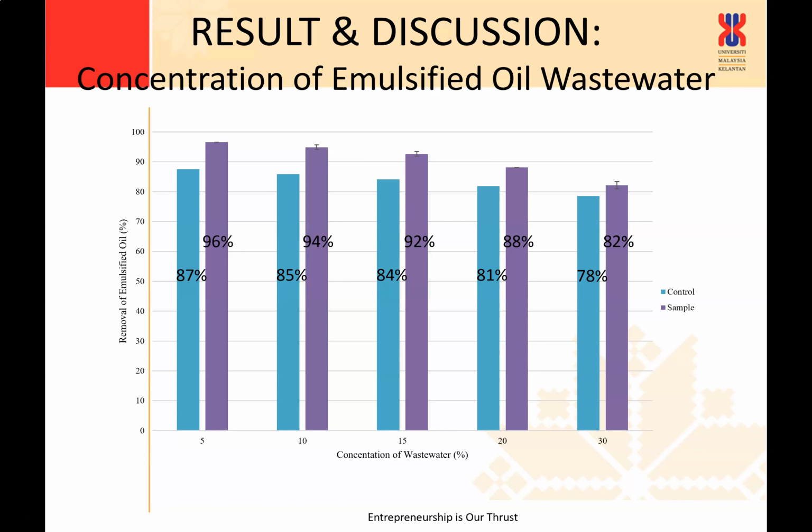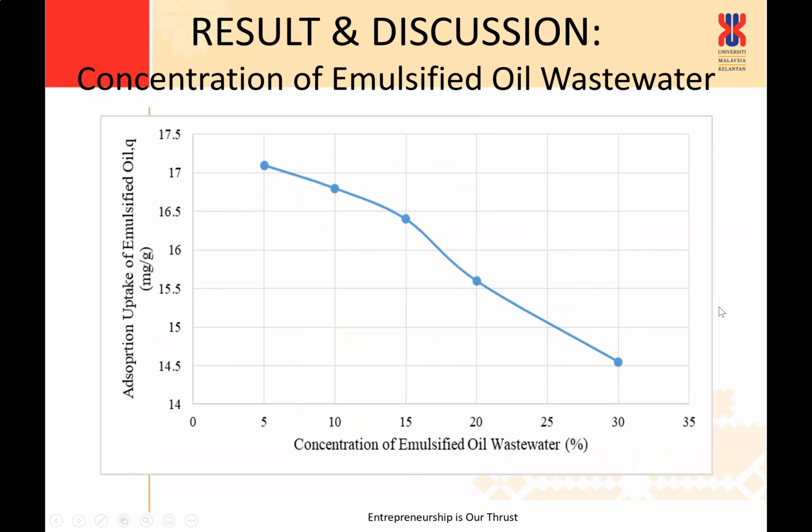In addition, a prominent decreasing trend was observed in this figure, which justified the decrease in oil adsorption uptake with increasing initial concentration of emulsified oil wastewater. These findings were in line with a study by Olufemi, which also reported a reduction of emulsified oil uptake via adsorption with higher concentration of emulsified oil wastewater due to fewer adsorption sites at higher oil concentration.